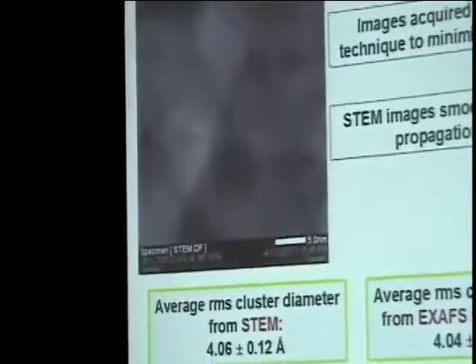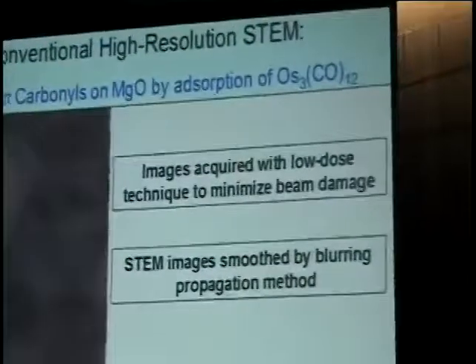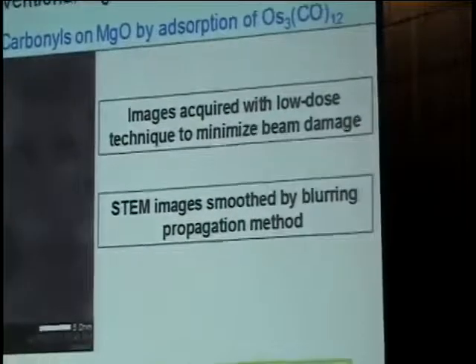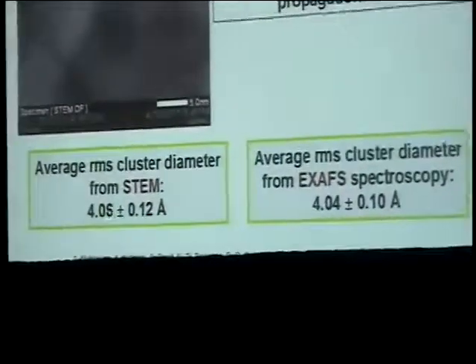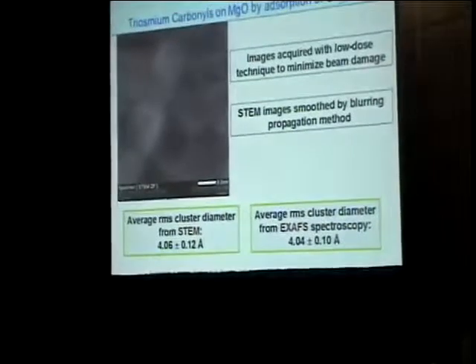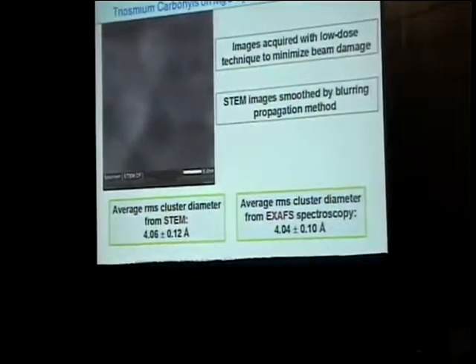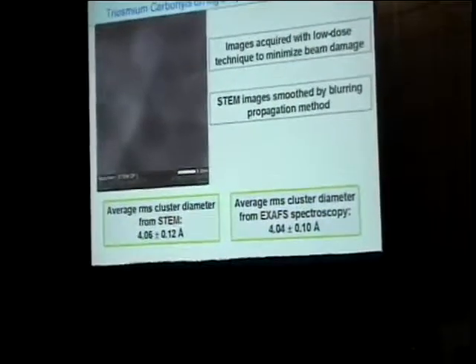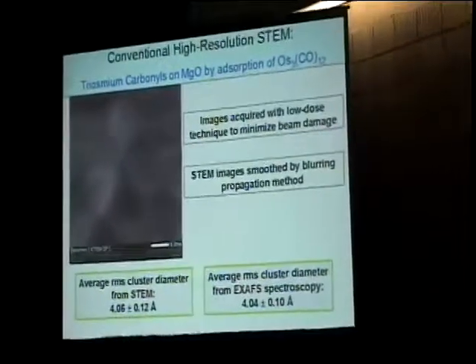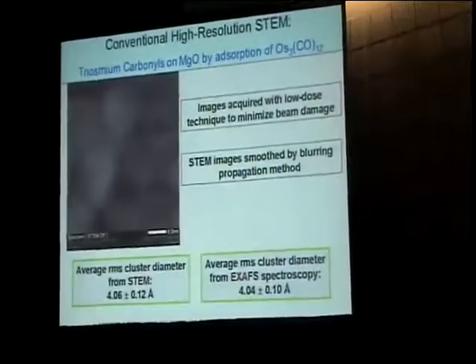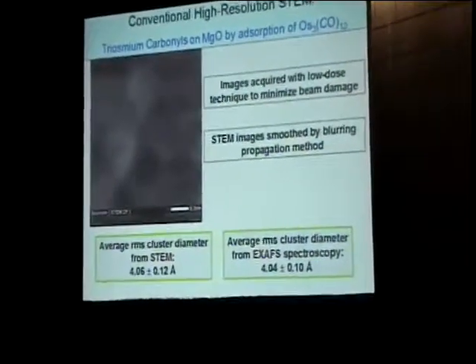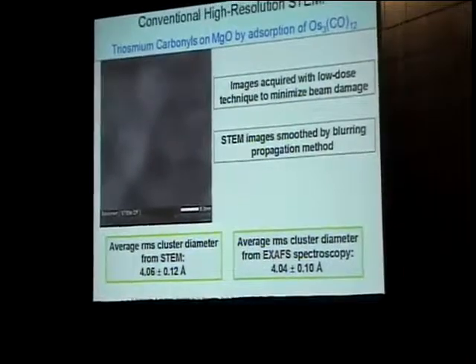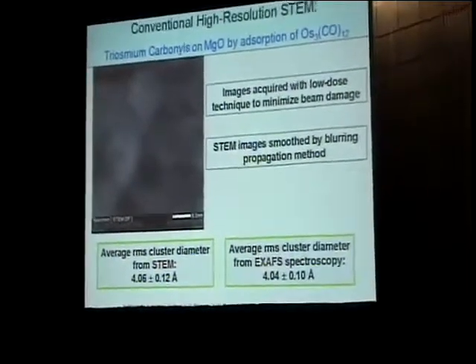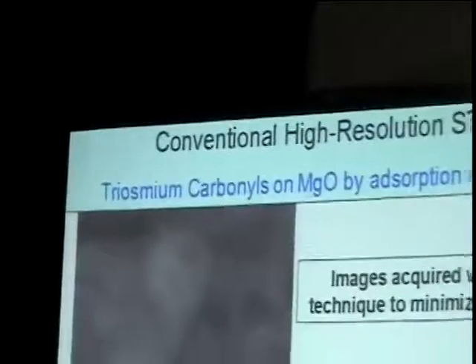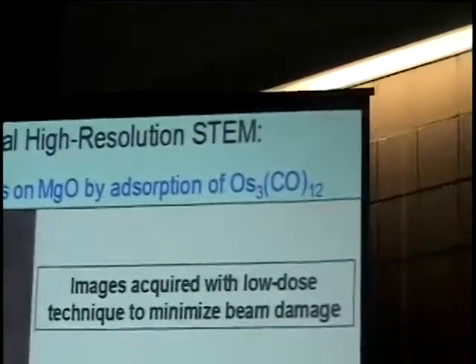And with a lot of data analysis, that I don't have time to go into, but it's involving smoothing and statistics, one can determine the average diameter of the supported clusters from the microscopy. There's that diameter. And if one determines spectroscopically what the predominant surface species are, and the infrared and the XAFS lead to that, then you get triosmium carbonyl, and it's lost one CO ligand and it becomes an anion. So it's still triosmium. So one can, using crystallographic data for that parent compound, calculate the dimensions of the clusters from the XAFS, and the values match.